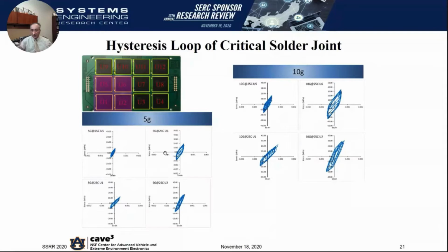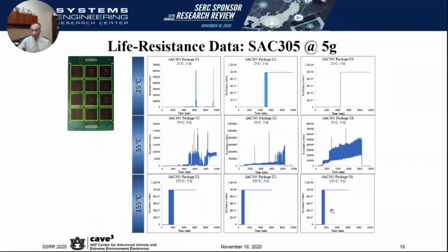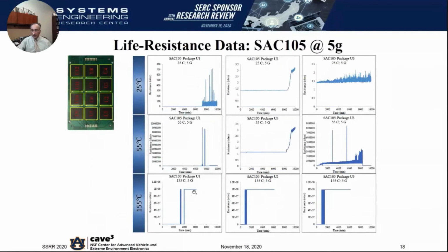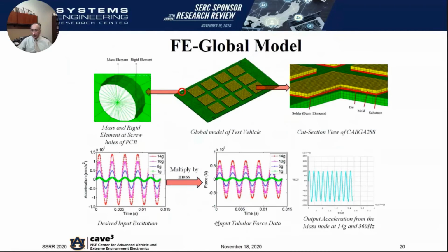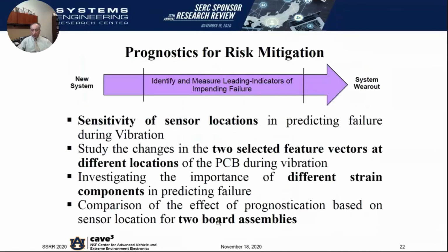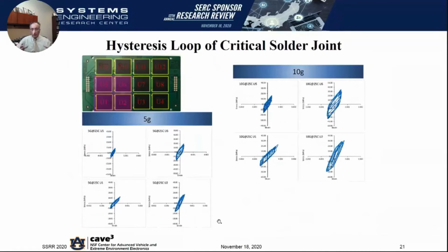So that tells us that the damage is accrued faster in the center locations, which is again what we saw here as well, where the time to failure was lower in the center location compared to the corners. So from that standpoint, the model captures the experimental data extremely well. So what we hope to be able to do is we hope to be able to take these hysteresis loops and mesh them with damage relationships to be able to predict life. So that's something that's still work in progress, and that has yet to be done. And once we have that, we'd be able to now predict life based on the amount of plastic work accrued per cycle of high temperature vibration.